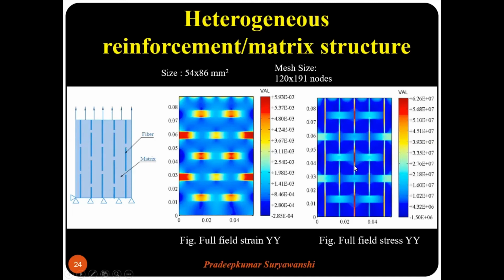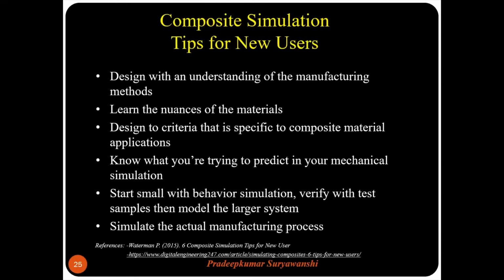Here again we can see full field stress, wherein again we can see the maximum stress is taken by the fiber material, and all these results are in line with the experimental as well as the results presented in the literature. Okay, so I'm done with my simulation results as far as my material model is concerned. That is our novel MSS model for simulation of deformable objects.